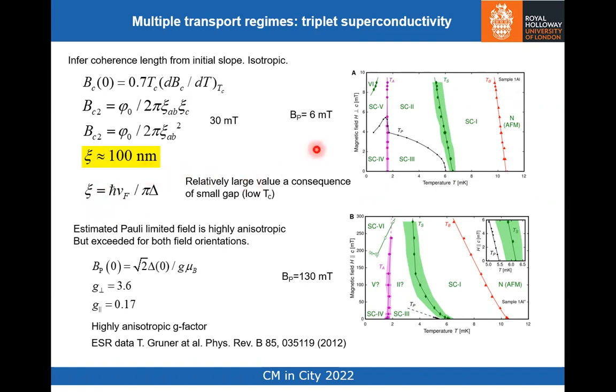Now if you work out, using the known g factors, the Pauli limiting field for this field orientation, it's 6 millitesla, and for this orientation it's 130 millitesla. So we're vastly exceeding the Pauli limiting field for both field orientations. For technical reasons, this field orientation was only studied over a relatively limited range of magnetic fields. But what you can see for field applied along the z-axis is that it starts out with this conventional linear suppression. That's where we get the coherence length from. But then there's this curvature. So it's an unusual field dependence of the critical field, which is reminiscent of what's seen in uranium ditelluride.